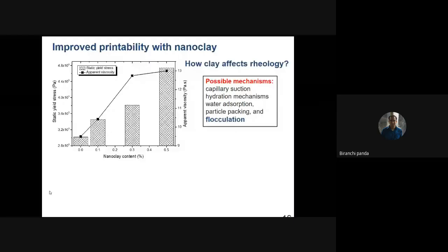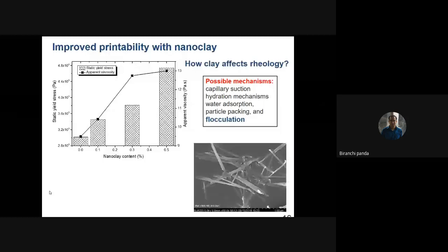And we investigated what the causes were, why it improved, and then we came to know that there is a mechanism called flocculation. Because of that, these nanomaterials are able to improve the yield stress of my control sample. The sample that I printed collapsed. Now the same material has more yield stress, more viscosity, but it is still in the printability zone, meaning I can print it without any discontinuity.